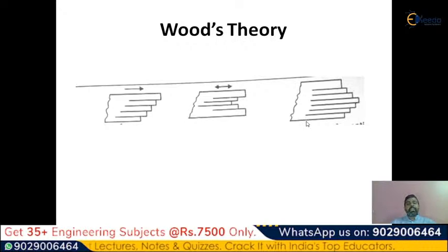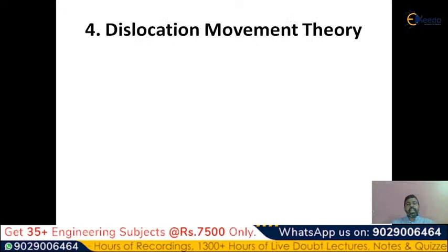Some bands move in the forward direction, some bands move in the backward direction. If this happens, Wood's theory says the crack will generate. These slip bands act as notches or edges. Automatically, the crack is going to be generated because of these slip bands. This is the mechanism described by Wood, and the crack will be generated, and ultimately the fracture is going to be observed in the material.